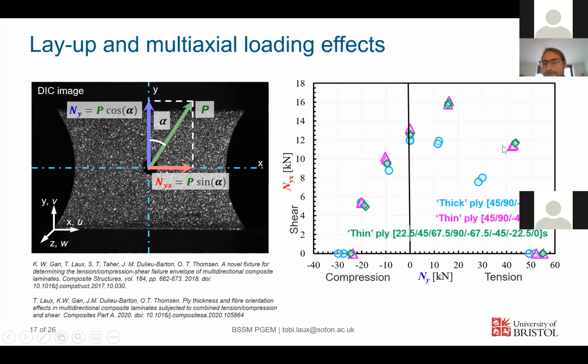And then we have layup 3. So here you can check the failure envelopes you drew. And so what we see here, which is really interesting, is that the specimen using layup 2 and 3, so the thin layups, is up to 150% stronger than the thick one, which is significant. What we also can see is that in compression shear, the difference doesn't seem to be huge. And what we also see is that actually, in terms of ultimate strength, adding these odd fiber orientations doesn't really benefit strength. And that, of course, informs the INEOS Team UK in what laminate to use where in the boat.